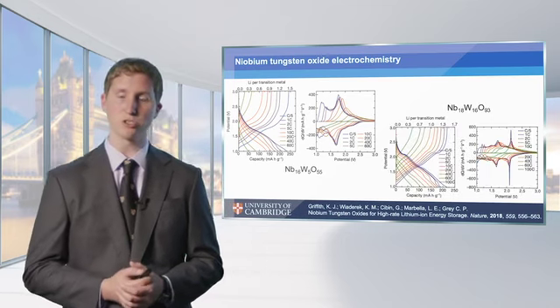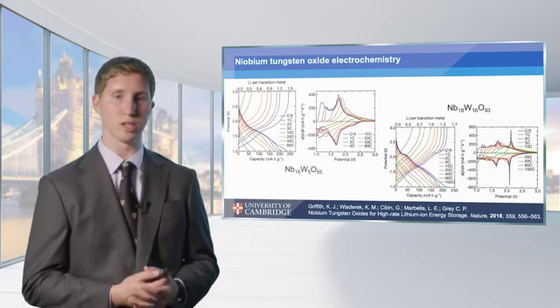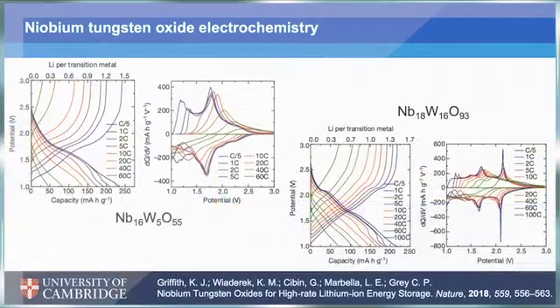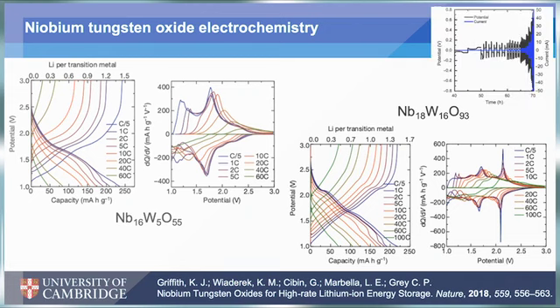And in the bronze structure, now the details of the discharge curve are different, and again raises interesting questions about what the differences in this material are, but the net electrochemical effect is very similar. We have an average voltage around 1.6 volts, and we're getting similar capacities out, including multi-electron redox from something in our niobium tungsten oxide. And one of the things that we noticed is that if you look at the initial part of the discharge curves, for either material, we have a large overpotential that's bringing down where we start lithiating. And so we wondered about the nature of this overpotential.